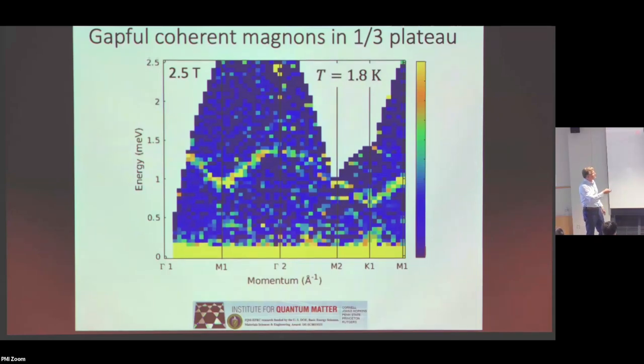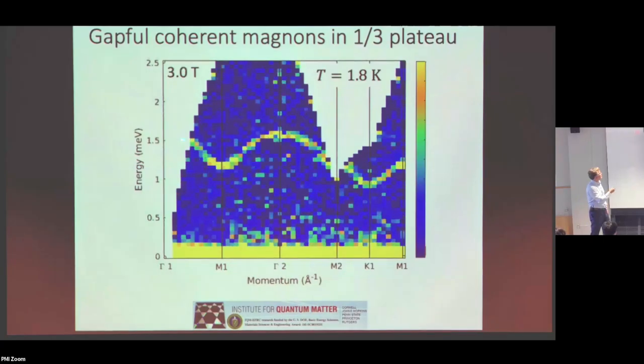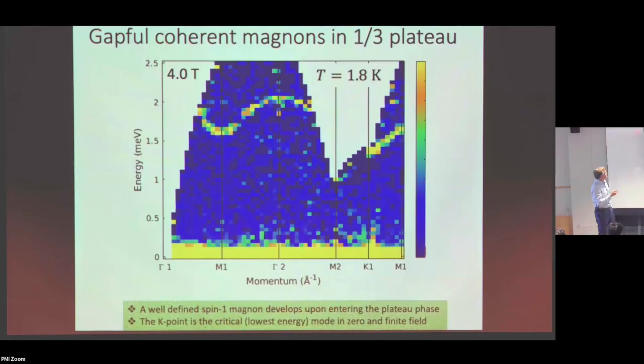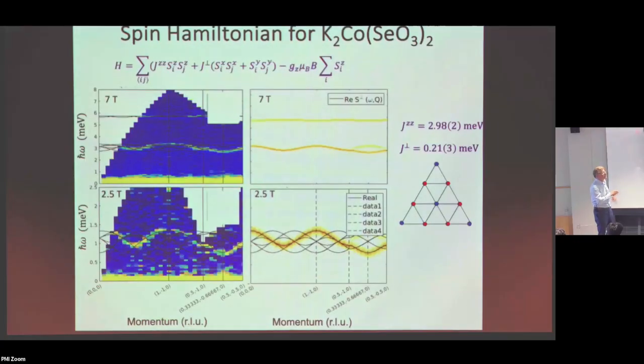And so this is the magnon, and actually here you can see the resolution. I mean, it's really tremendous resolution, very, very different from the continuum scattering that I showed you previously. It's not because we don't have the resolution to see it, it's because it truly is broad scattering. But here we have a single particle excitation, and now we can use that to actually determine the exchange constants. I won't spend very long emphasizing that, but it's really very important.